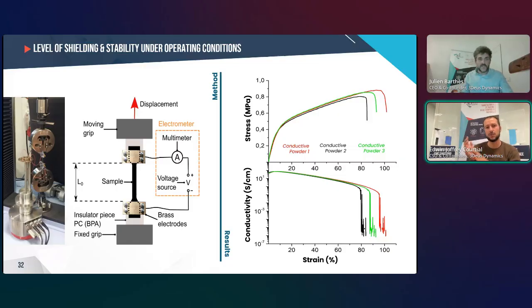To evaluate how stable the electromagnetic shielding remains under mechanical load, we developed coupled tensile-electrical measurements. The setup combines a standard tensile test with in situ conductivity monitoring through brass electrodes, a customized version of the ASTM D412 mechanical protocol. Here, we don't measure the shielding directly, but the electrical conductivity, which correlates to the electromagnetic performance throughout deformation. In short, stable conductivity under strain means a stable conductive network and therefore consistent shielding capability during use. The plot on the right shows both the mechanical and electrical behavior of different silicone-filler composites.